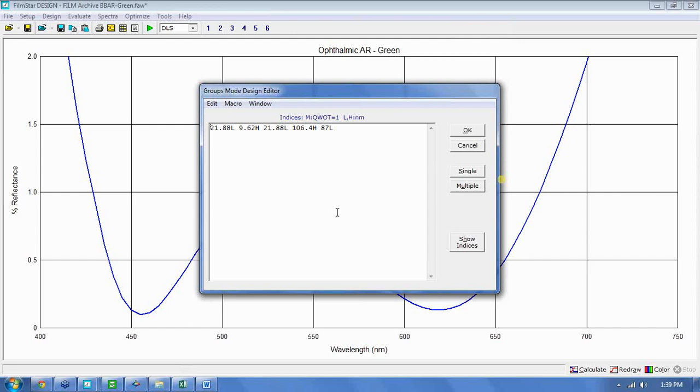The lens material, if you're coating glass, if it's BK7, if it's SF6 or something like that, you want to make sure that whatever you're dipping your lens in to strip isn't going to actually attack and ruin your glass, which you may already know. SiO2, TiO2, hafnium oxide, aluminum oxide, they're all soluble in different acids or bases.